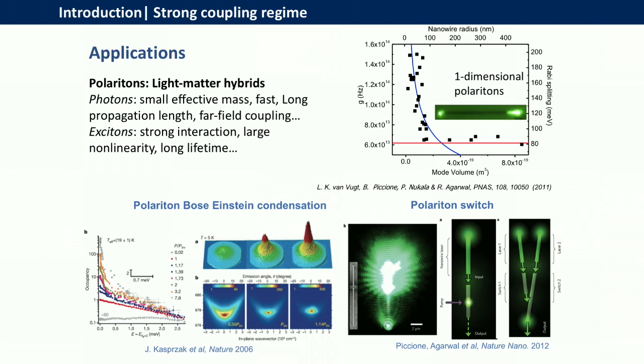So we basically showed, now it's been almost 7 or 8 years, that if you take a nanowire, and we measured the light matter coupling strength, so we had to develop new techniques. What we found was if we take a material like cadmium sulfide, then the light matter coupling strength does not change pretty much if the size of the material is the size of this room or down to 400-500 nanometer length scale. So the system behaves like a three-dimensional polariton. That's the natural excitation of a cadmium sulfide semiconductor. But below a certain size, around 200 nanometers or so, the system suddenly transitions from a three-dimensional polariton to a one-dimensional confined polariton,